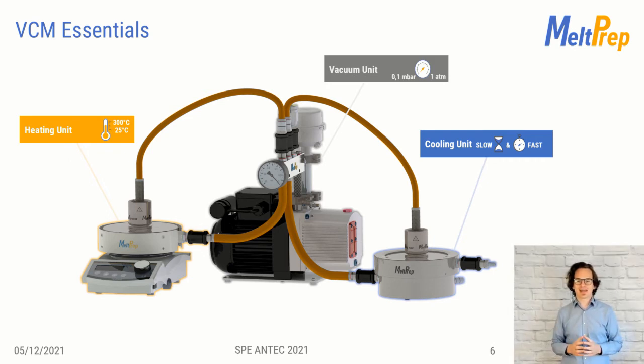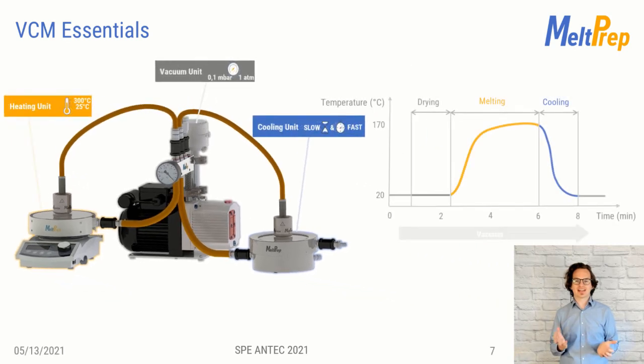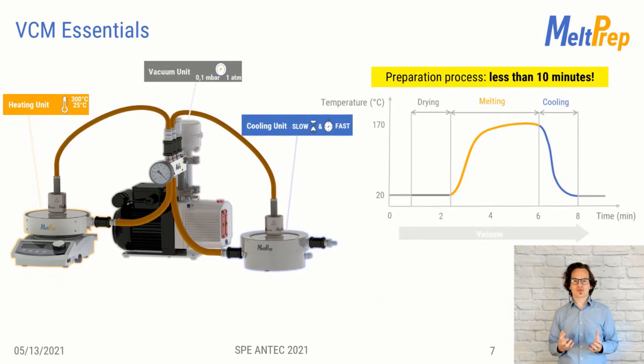Here you can see the entire VCM Essentials again. A typical sample preparation takes less than 10 minutes. Heating is performed in some minutes and can go up to 300 degrees Celsius, making it suitable for most R&D applications. Cooling generally also takes only some minutes. At the end of the operation, there is no tedious cleaning required, making the process time efficient and lossless.